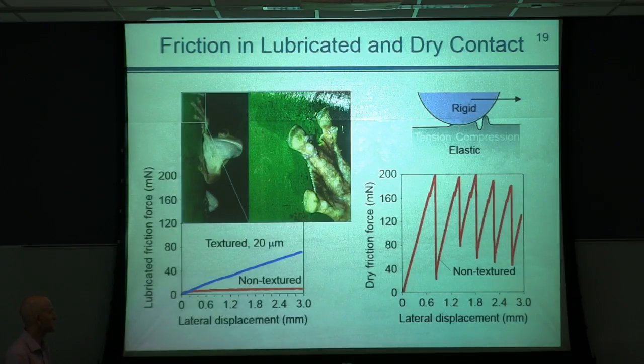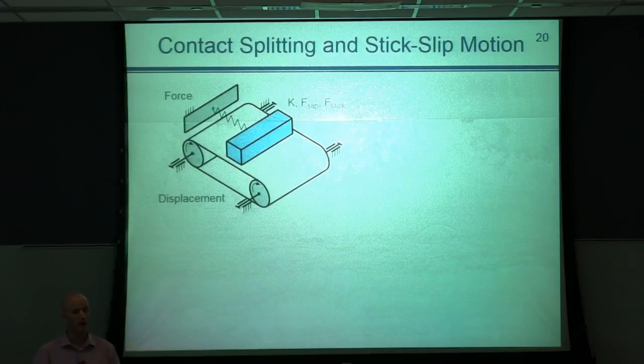This leads to stress relaxation, and the surface actually moves not as a result of sliding, but as a result of worm-like displacement at the interface. So this is how a smooth surface operates. And surprisingly, the textured surface, these samples with hexagons, appeared to slide in a smooth way. In order to explain this behavior, we developed a toy model that in a very simple way allows us to explain that the reason is statistical variance in properties of the surfaces that come in contact.